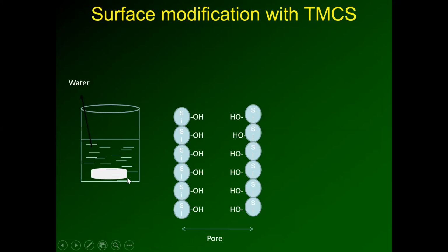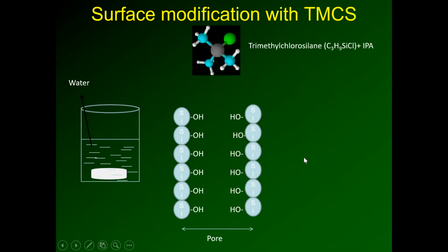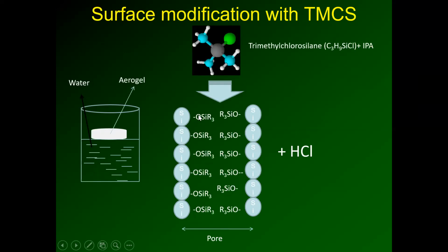So you can see the aerogel made like this absorbs water and goes to the bottom of the water. So this is the aerogel. Now you do the TMCS surface modification. Because of this, all the unsaturated oxygens become saturated. Then you can see immediately this aerogel has become hydrophobic from hydrophilic. It will only float, it will never take any water inside.